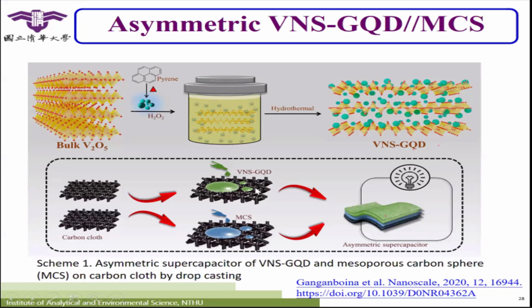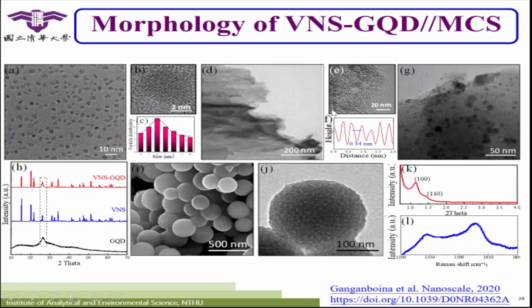And then we try to fabricate our negative electrode. We use carbon cloth and then put some three-dimensional material on it. We call this one the mesoporous carbon sphere. You will see their morphology here. So one electrode we use is the VNS with graphene quantum dots, and the other electrode we use is the mesoporous carbon sphere. We merge them together, and we call this one an asymmetric supercapacitor. Their values will be here. This one is the case with the VNS and graphene quantum dots, the upper part here. The lower part is another case, the MCS mesoporous carbon sphere, so that we can see the sphere here.